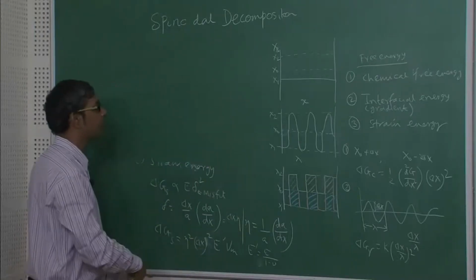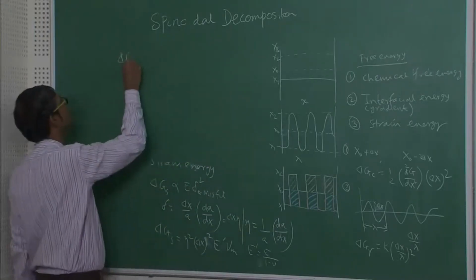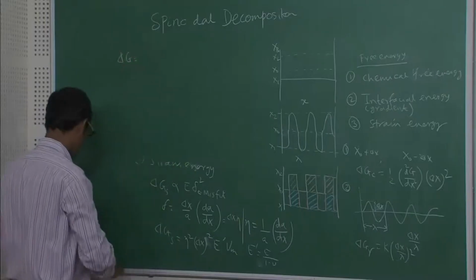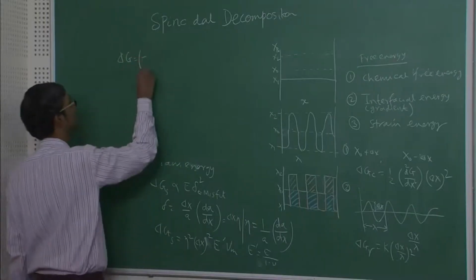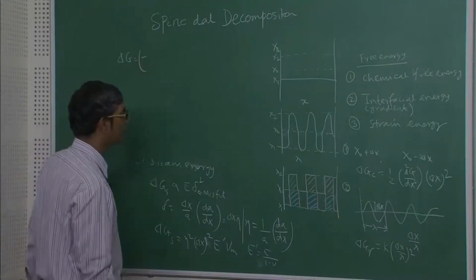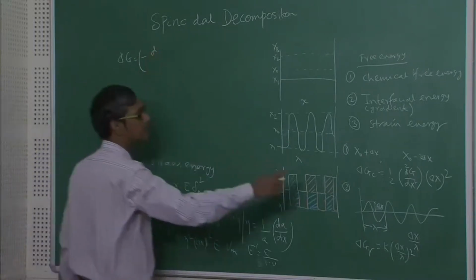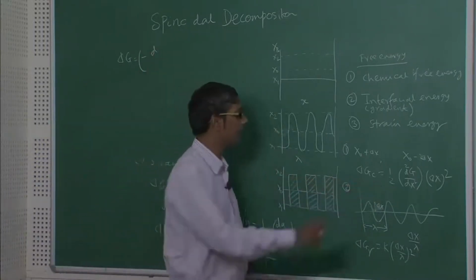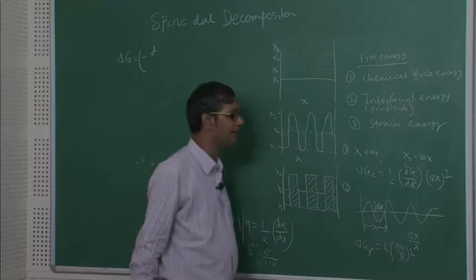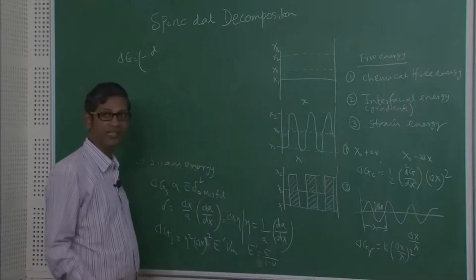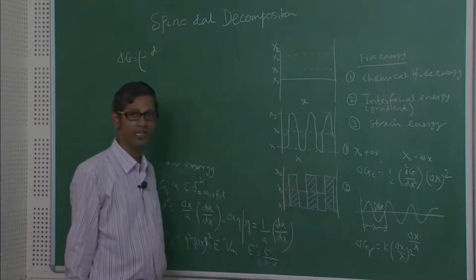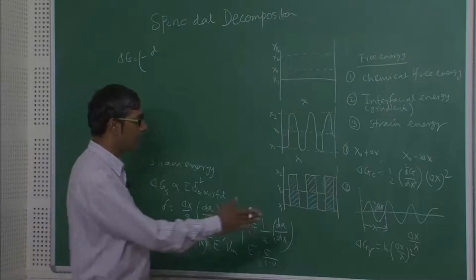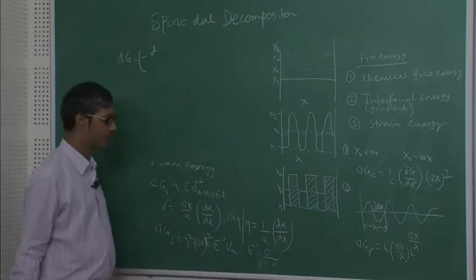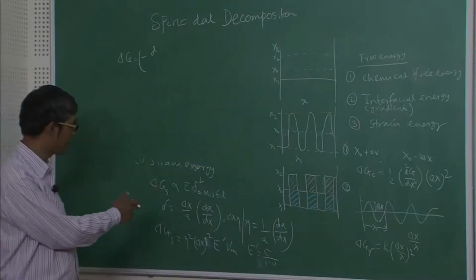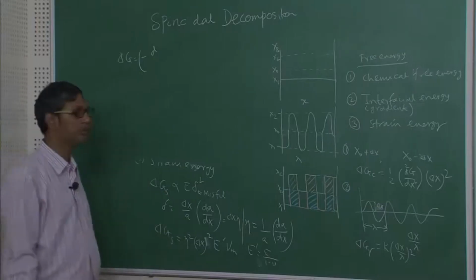So let us put them together. So total energy of the system G can be written very easily like this. Remember this energy is minus, why? Chemical free energy is always minus, we do not write it but it is always negative, because that is what is driving the whole system for transformation, right. On the other hand, these free energies are positive terms, the gradient energy or the interface energy and the strain energy, that is the convention we always use.